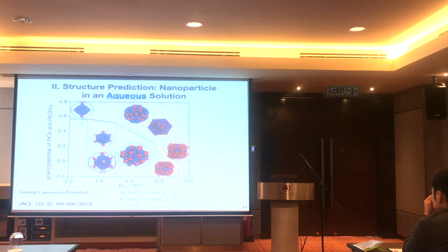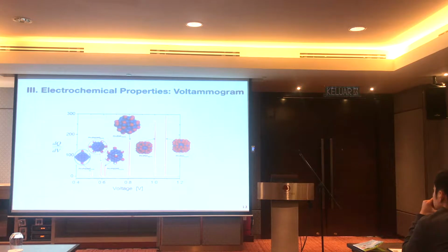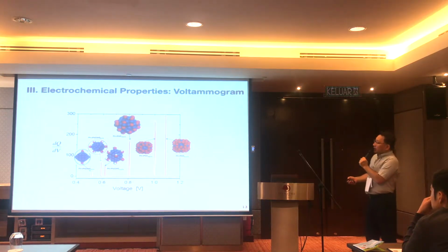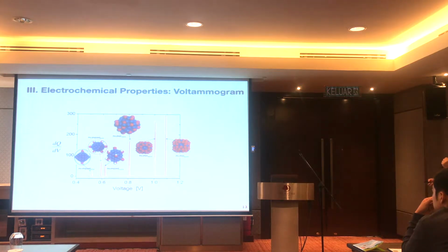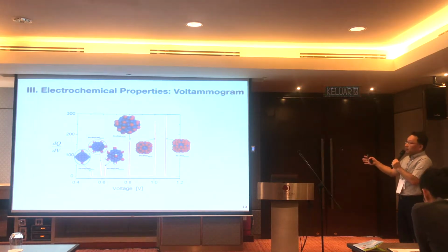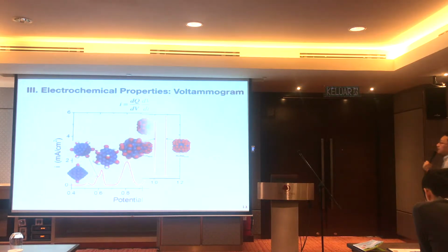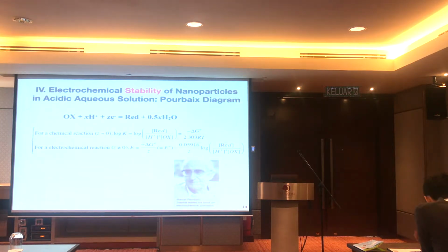This figure shows that this was done, the first in the world. Also, you can predict experimental measurements. How many people understand the cyclic voltammogram here? If you increase the chemical potential, the electron potential, you're going to see this peak. You can measure the peak in the experiment, and you can predict any peak. What is the structure of the platinum nanoparticle in aqueous solutions? If you give this map to experimentalists, they can validate our result accurately. The other topic is how platinum is unstable in the nanoparticle regime in aqueous solutions.